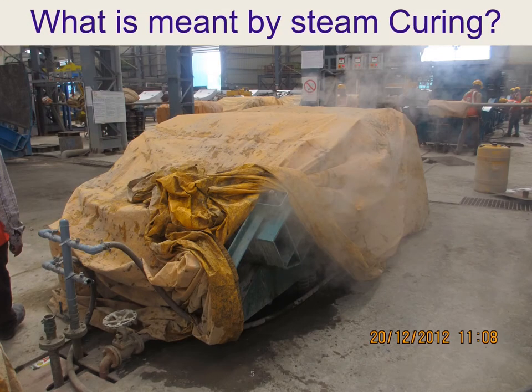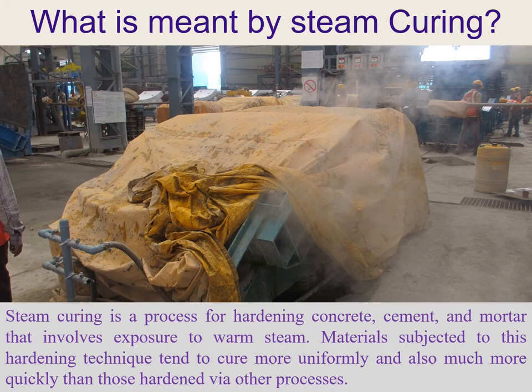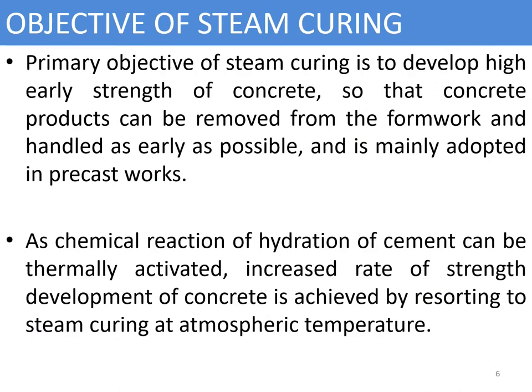Steam curing is a process for hardening concrete, cement, and mortar that involves exposure to warm steam. Materials subject to this hardening technique tend to cure more uniformly and much more quickly than those hardened via other processes. The primary objective of steam curing is to develop high early strength so that concrete products can be removed from the formwork and handled as early as possible. It is mainly adopted in precast works, as the chemical reaction of hydration can be thermally activated to increase the rate of strength development.